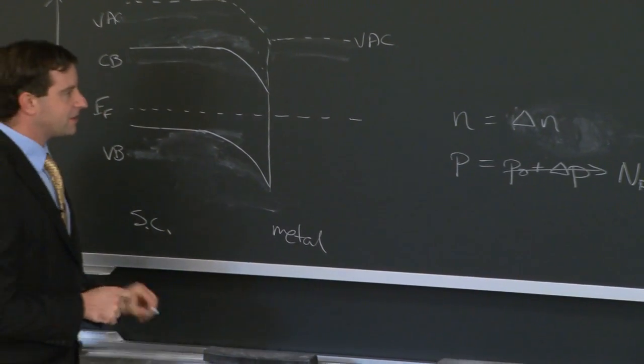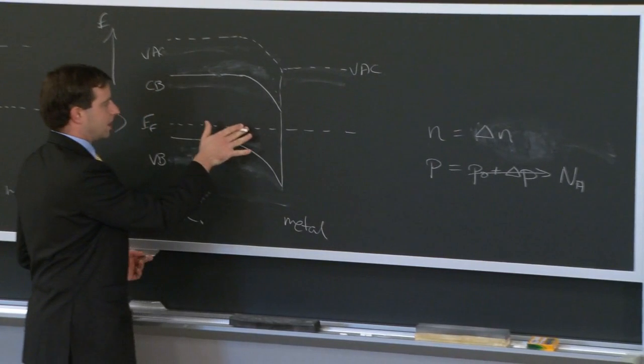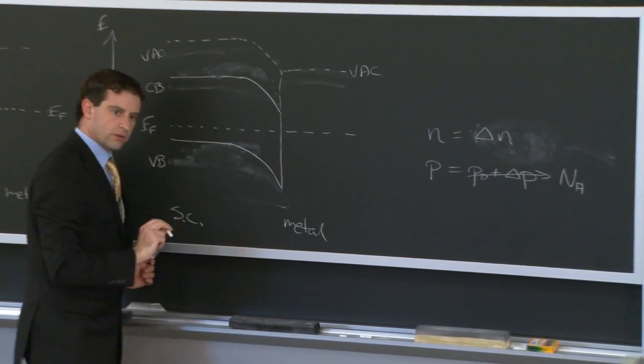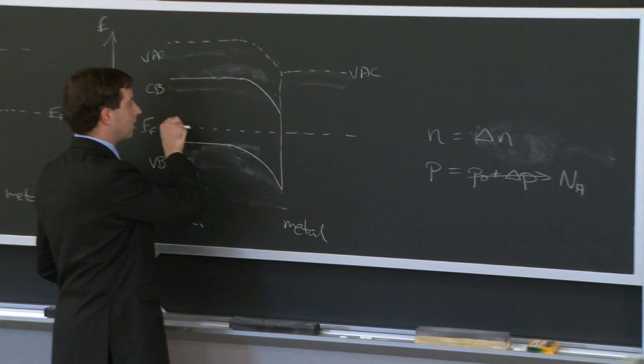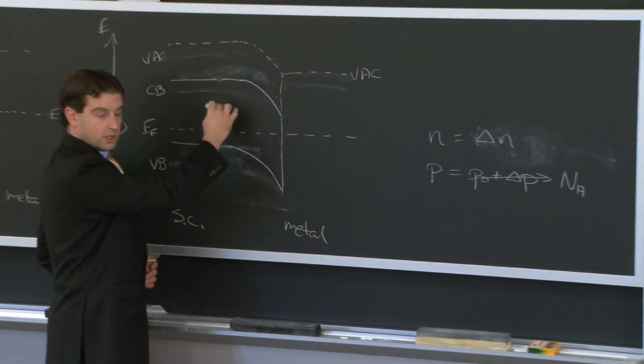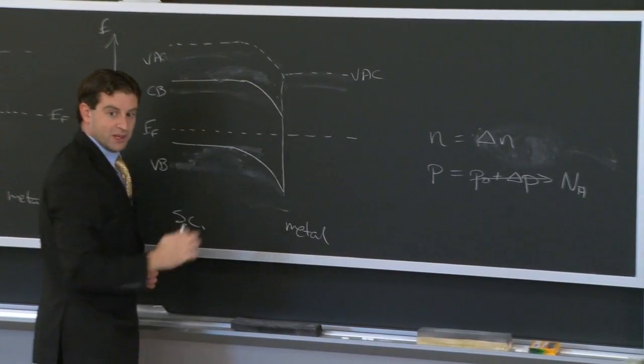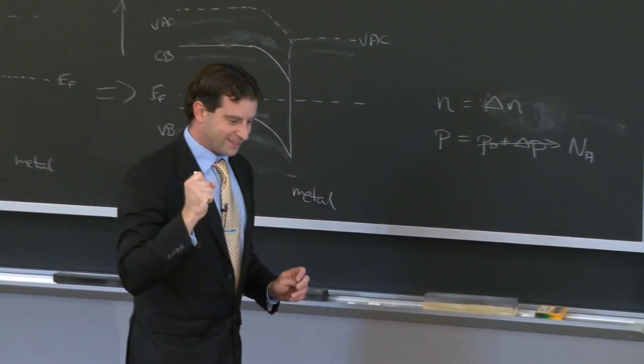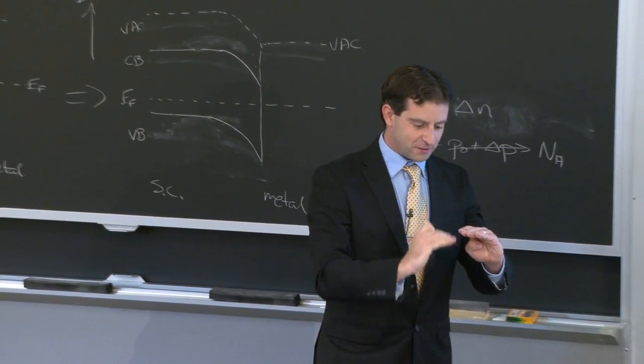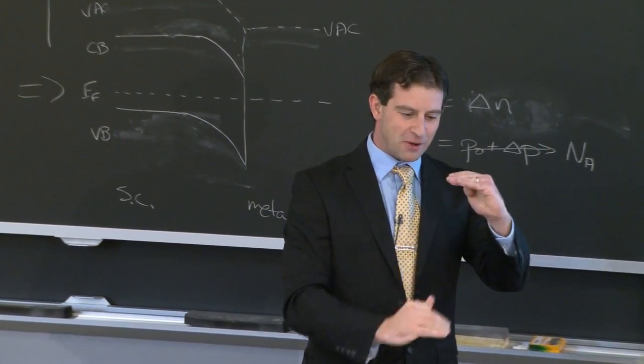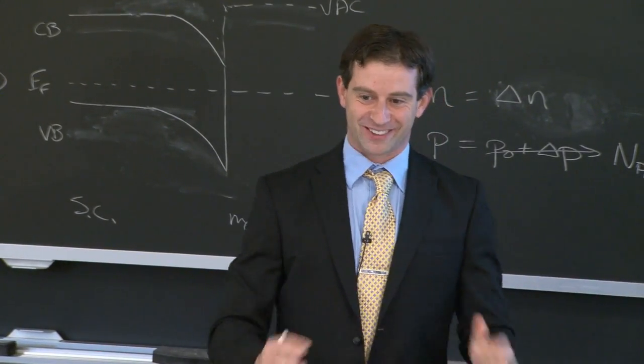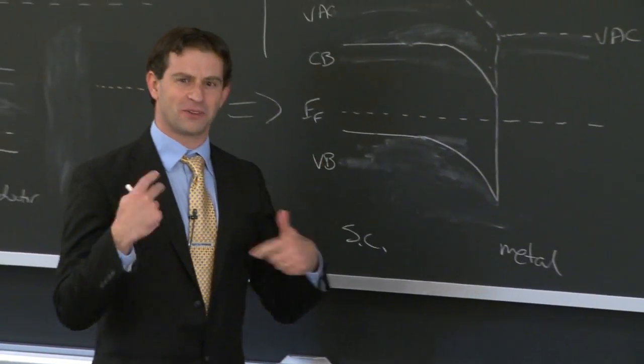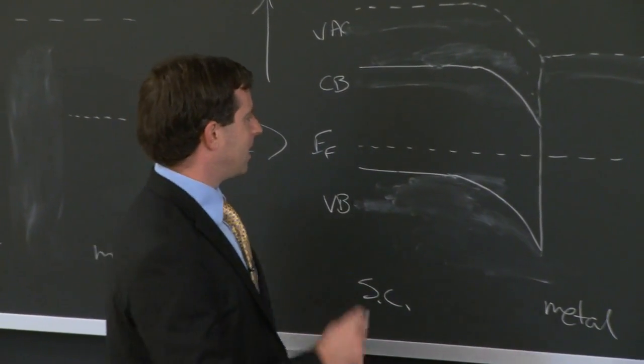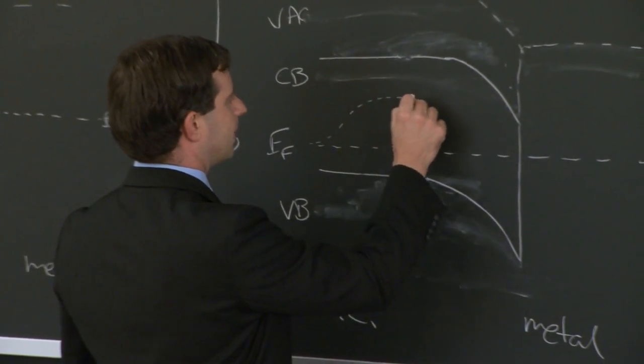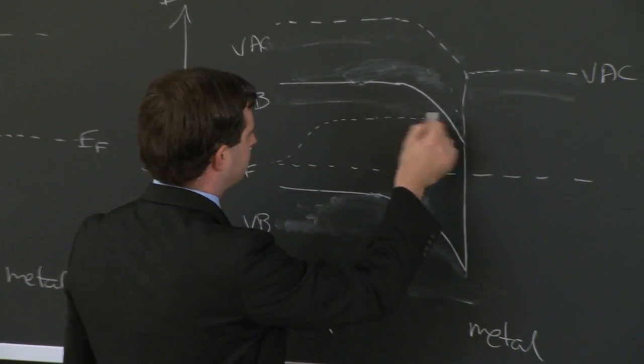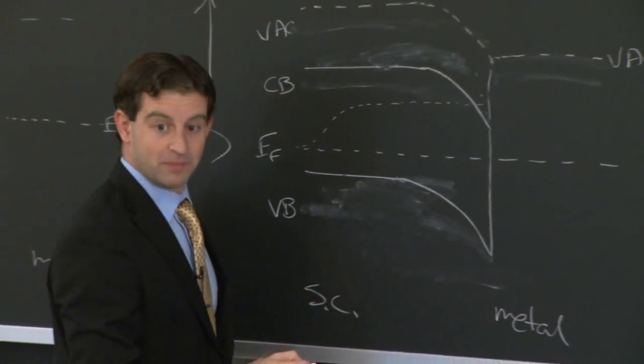And so what we have at the end of the day is a separation of the Fermi energy between electrons and holes. The Fermi energy for holes is going to be relatively constant, but for the electrons, the minority carrier, you'll have a rise of that quasi-Fermi energy because now you're filling in more of the electrons up here. And so the Fermi energy, as defined as the energy state that has a 50% occupancy probability, is now at a different energy for electrons and for holes. Awesome. It's really one of those things that takes a while to wrap your mind around. And so now we might have a situation in which my electron quasi-Fermi energy is somewhere up here.